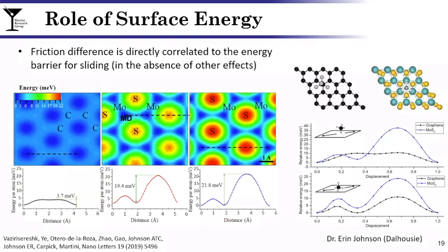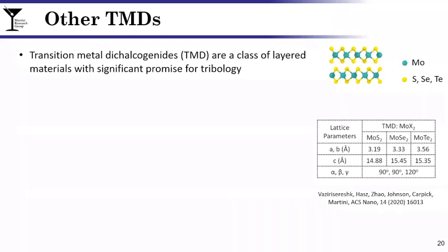So you may be thinking, well, sure. There's lots of differences, though, between MoS2 and graphene, right? Not just their crystallographic structure, and potentially not just their energetics. So we took one step further, and we performed a study comparing transition metal dichalcogenides. This is a class of layered materials of which MoS2 is one. Here we compared 3 different TMDs, with sulfur, selenium, and tellurium, to get MoS2, MoSe2, and MoTe2.